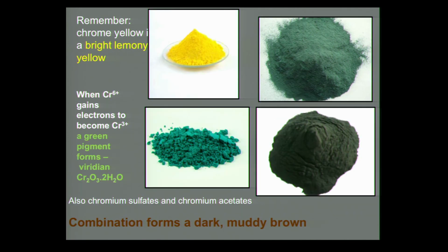Well, remember that chrome yellow is actually this nice, bright, lemony yellow color, but it turns out that when chromium 6+ changes to chromium 3+, then a new chromium compound is formed, which is also an artist's pigment. It's a green pigment called viridian, and that's what's shown here. But then we also have chromium sulfates and chromium acetates forming, and these are shown here. When you mix all these compounds together, unfortunately, you get a dark, muddy brown color, and that's what we're seeing on the surface of the painting.